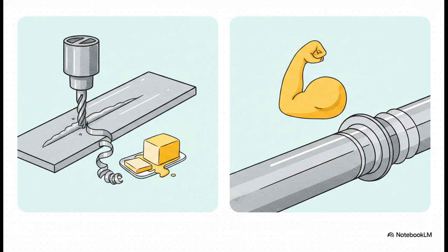Do you need it soft and machinable for a single pass? Go pure nickel. Do you need serious strength, multi-pass capability, and tolerance for high phosphorus? You've got to grab the nickel-iron rod.